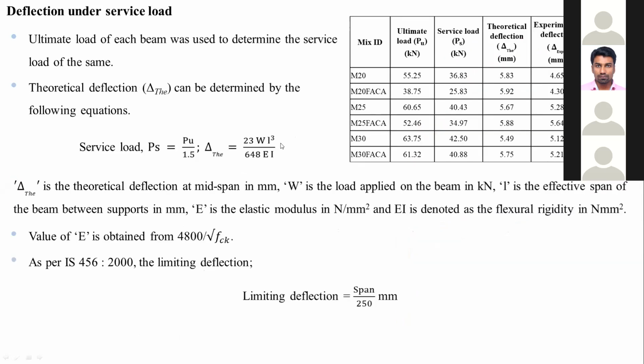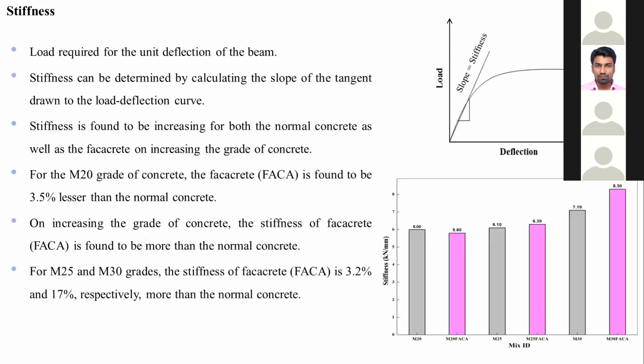We've also found deflection under service load, and it is essential to find out how the structure deflects under the service load. We found that the stiffness is increasing on increasing the grades of concrete. And for M25 and M30 grades, the stiffness of Fakakrit is 3.2% and 17% respectively more than the normal concrete. That validates our result, and that the Fakakrit is stiffer and more brittle.